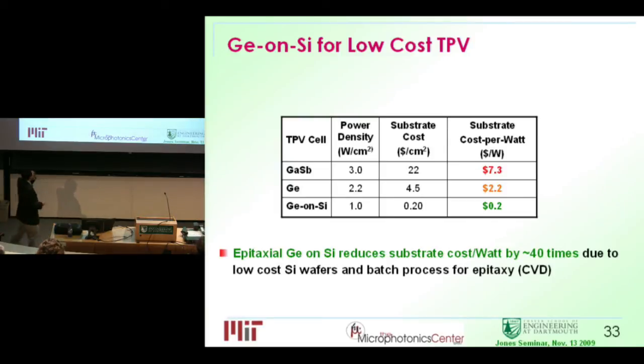So what's the problem in this case? Turns out gallium antimonide is a very, very expensive material. We usually base this on a single crystal material, but a 4-inch wafer can cost you $1,500 or so. So if you calculate the dollars per watt just from the substrate contribution, that is pretty high. That is almost 100 times higher than fossil fuel generation. So people are thinking about using a germanium single crystal substrate, but still it's relatively expensive. So we have a 6-inch wafer that costs $800. So still not very feasible.